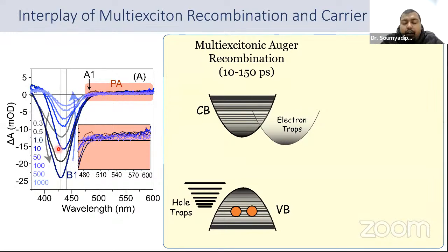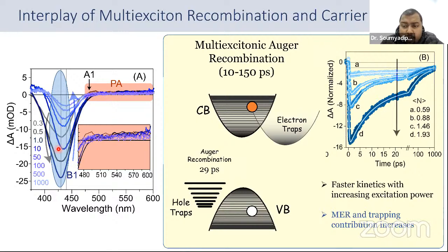Okay. Now, the second thing going on is multi-excitonic Auger recombination. You have to understand, Auger recombination, although it's a recombination process, is non-radiative. What happens? You excite the electron, then the electron goes up, and through intraband relaxation comes to the lowest vibrational energy level of the excited state. Then it can recombine. When it recombines, it loses some energy. That energy is not radiative. It's a non-radiative energy, and that energy actually excites the other electrons in the excited state to go up to a higher energy level. This is called Auger recombination, and this happens around 30 picoseconds.